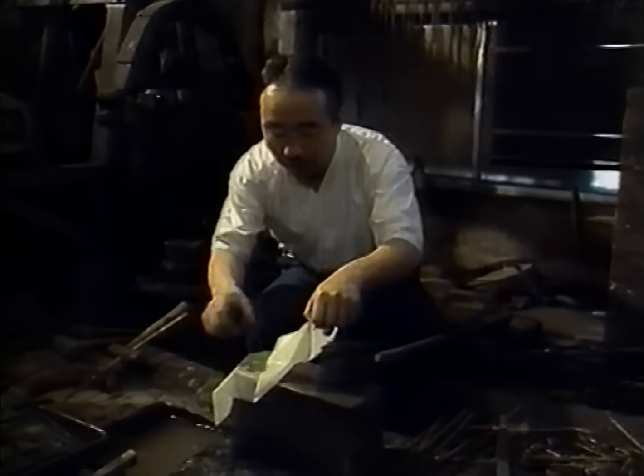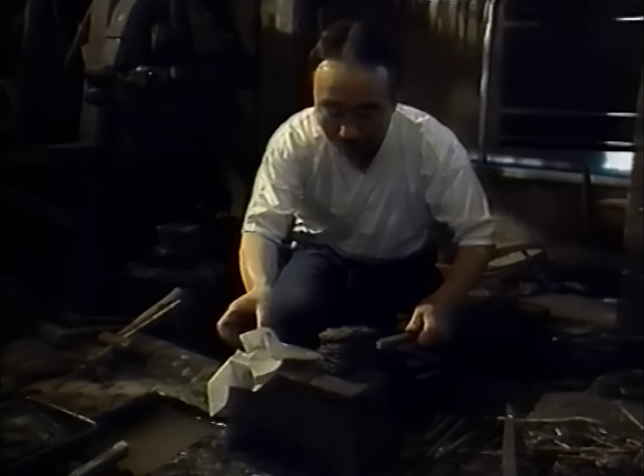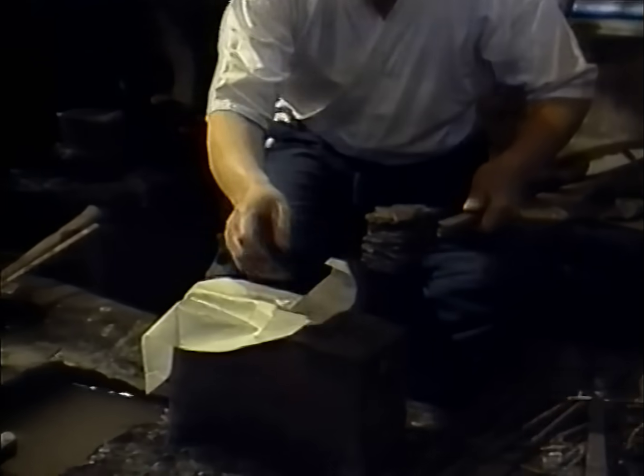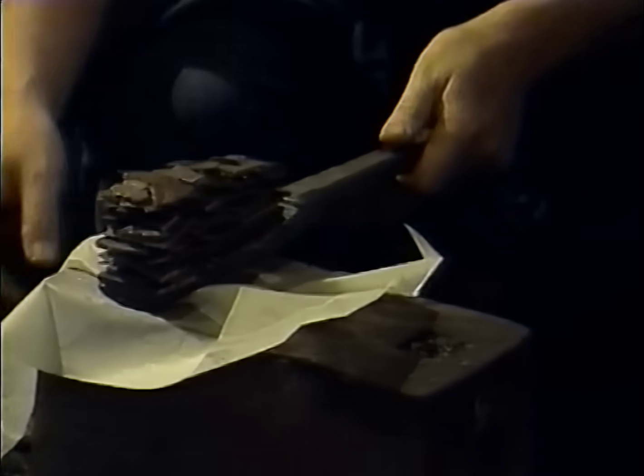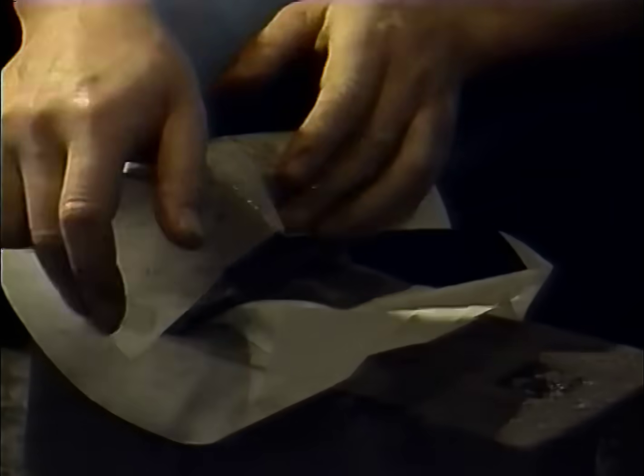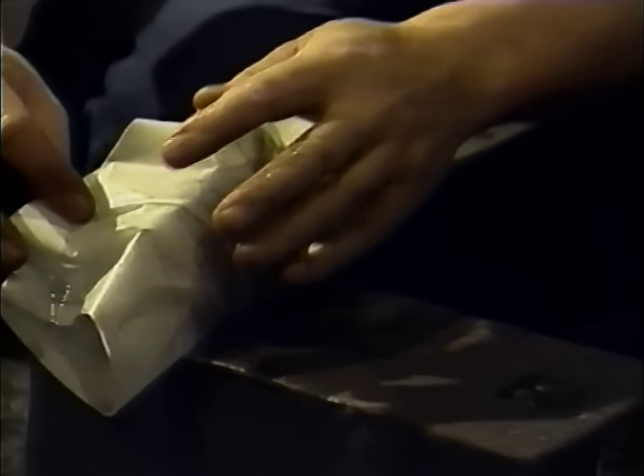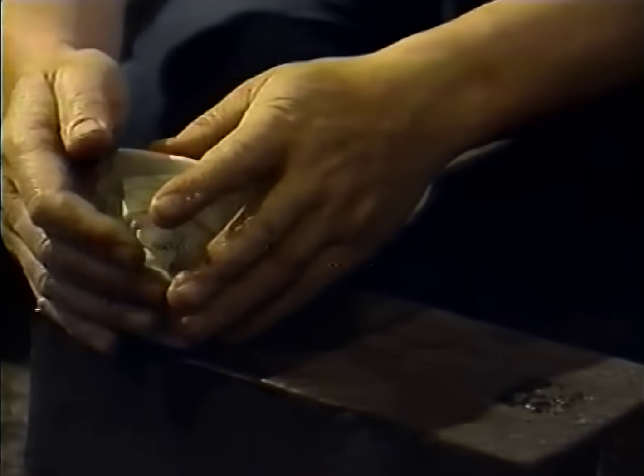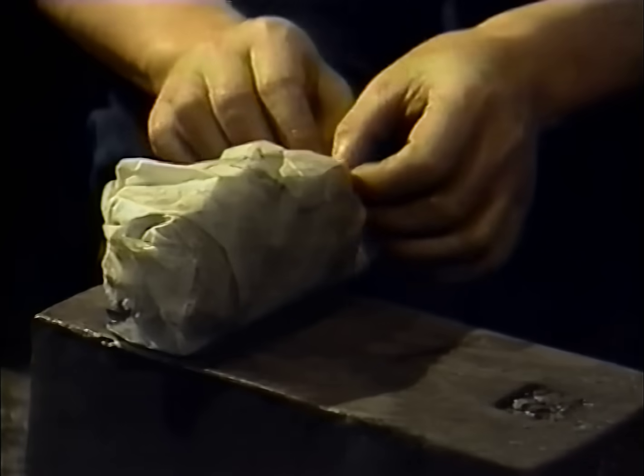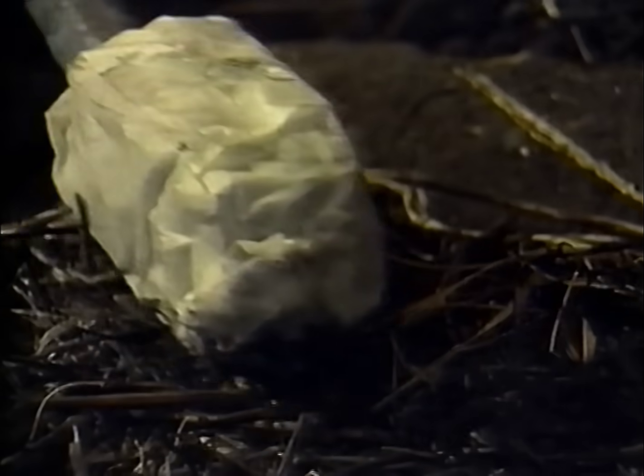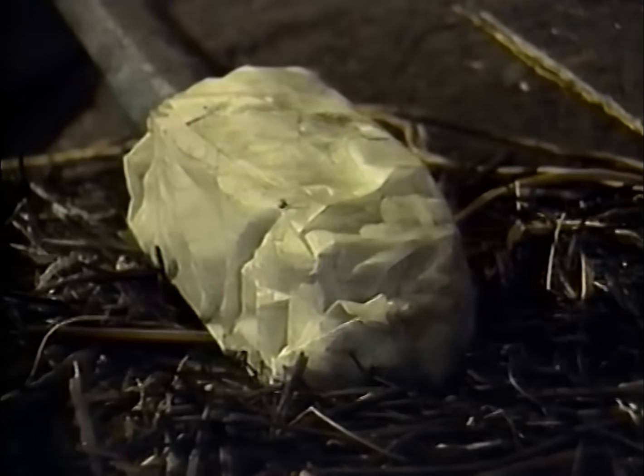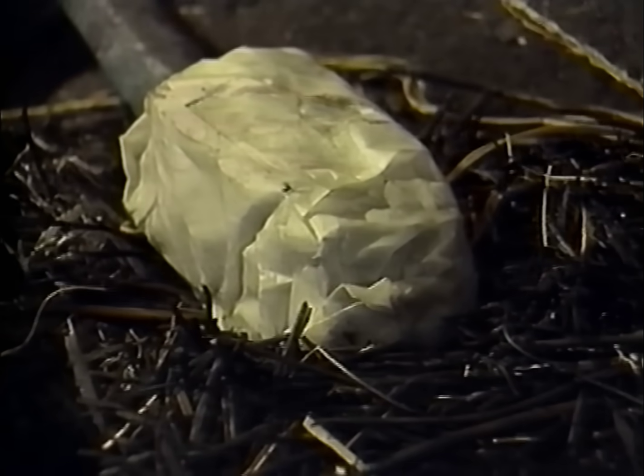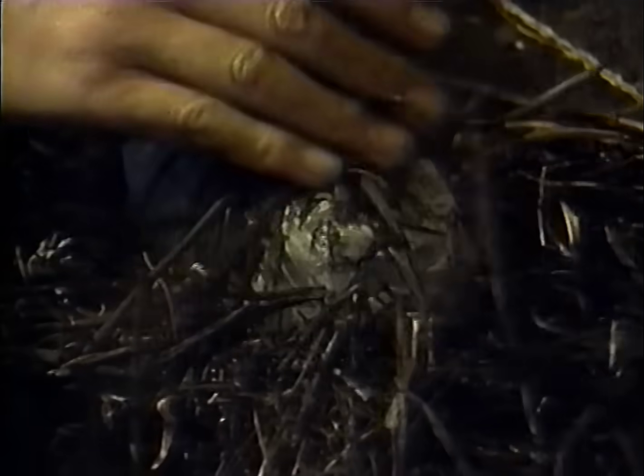The steel wafers are skillfully arranged on top of the tekogane plate to make a block of steel. To prevent the wafers from spilling over, collapsing, or falling off, the smith carefully wraps the block with wetted Japanese paper. The black wara ashes are coated onto the paper-wrapped bundle. This helps compensate for the loss of carbon that occurs with heating.